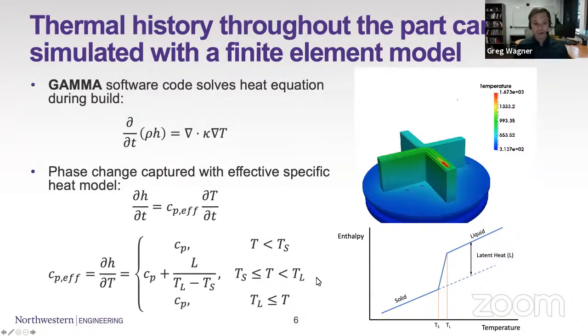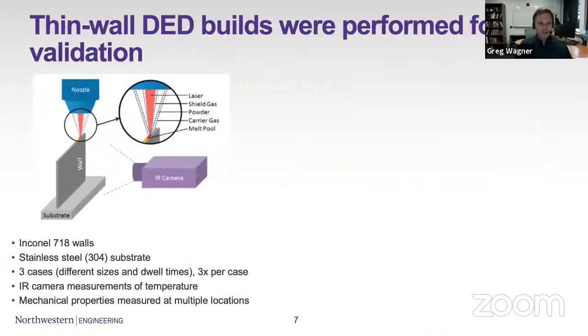So the model itself is fairly straightforward. One problem with models like this, if you've worked with them at all, is validating the temperature history out of these. There are still very few ways to get detailed and accurate temperature measurements from an additive manufacturing build, whether it's the directed energy deposition or powder bed fusion process. It's hard to get thermocouples or things like that very close. So one way where this can be done, at least with some relative accuracy that takes some calibration, is through IR camera data. So we've taken advantage of this in order to try to validate our part scale models.